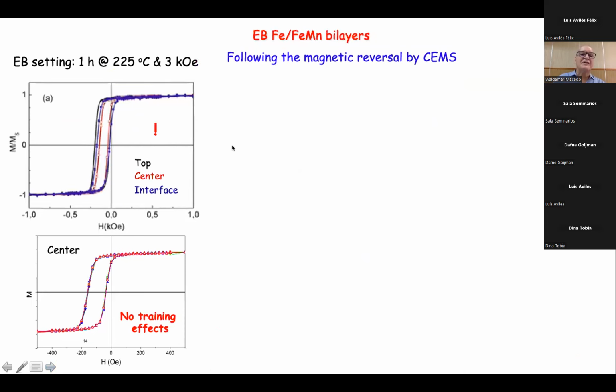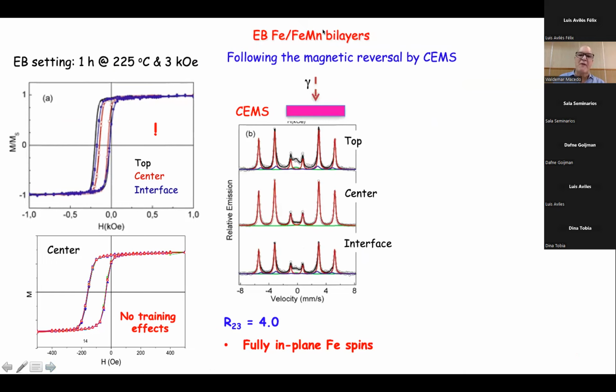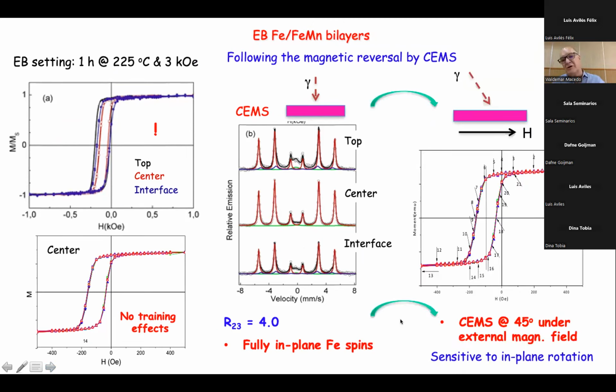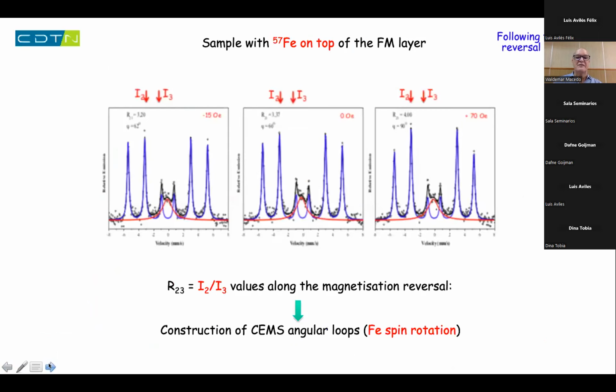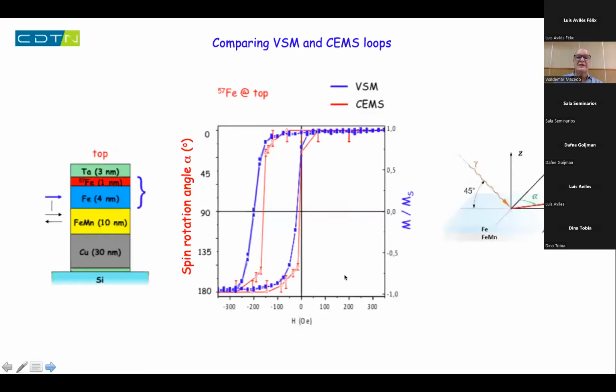What was very difficult in this system was to get equivalent samples, because the preparation is not trivial. Preparing equivalent samples was really a nightmare. After getting samples prepared by sputtering with iron-57 in different layers, we could go on to do Mössbauer. The normal Mössbauer shows that these samples are fully in plane, so you have to go to a non-perpendicular geometry to be sensitive to in-plane rotation. Then you can record the Mössbauer spectra, apply a magnetic field, and from the R23, or the line intensity ratios, you can construct hysteresis loops for the iron spin rotation. This is what we get.